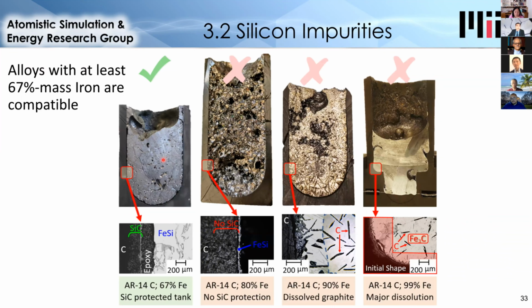However, when I tested iron in these small tanks under isothermal conditions, without the non-isothermal circulation, we found that we could contain up to 2/3 iron by mass. And this is really important because this reduces the cost of the system by 2/3 essentially, because iron is so cheap and its volumetric energy density reduces the size of the system.